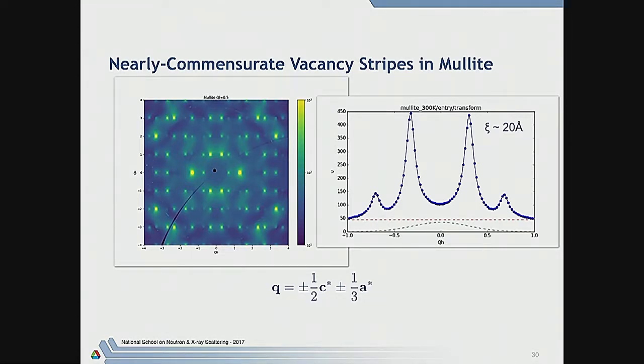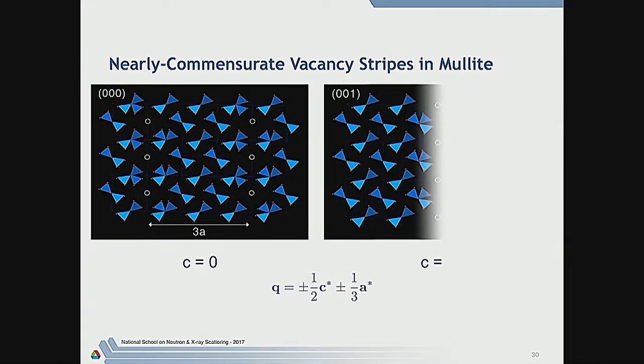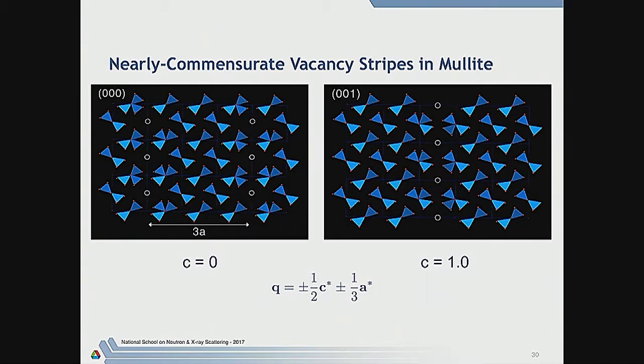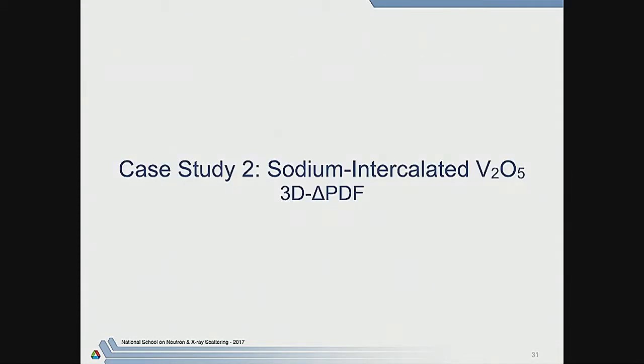so for instance, in Welberry's model, he didn't predict these stripes, but they're actually present in the data and in the ab initio. So I think basically the point is that the way that diffuse scattering was analyzed in the past, the total volume of diffuse scattering was well modeled by these short-range order parameters, but there might have been details associated with the longer-range correlations that were missed, and which the ab initio calculations got right.